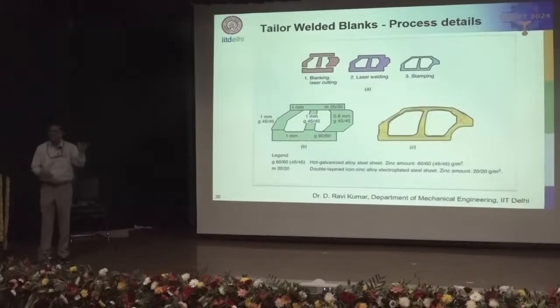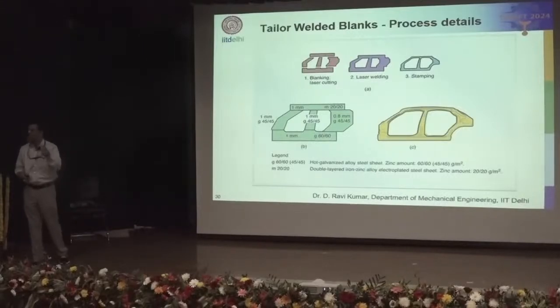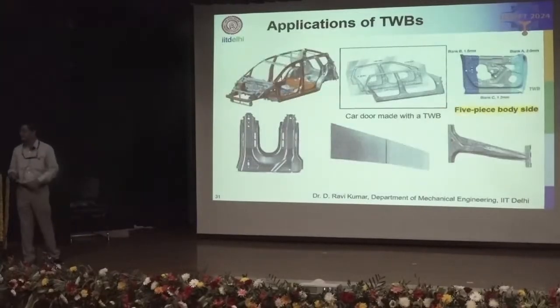So wherever you require higher stiffness, we can have a higher thickness. And wherever you require higher strength, you can use a high strength steel grade, and in other portions you can have a low strength grade. So because of this flexibility, the tailor welded blanks have found a lot of applications in automobiles. So here you can see a blank with a laser weld, and then it is formed. You can see the weld line here. So this gives you a lot of flexibility, and here also we can see the weld line.